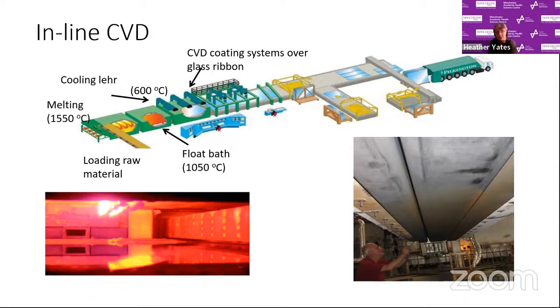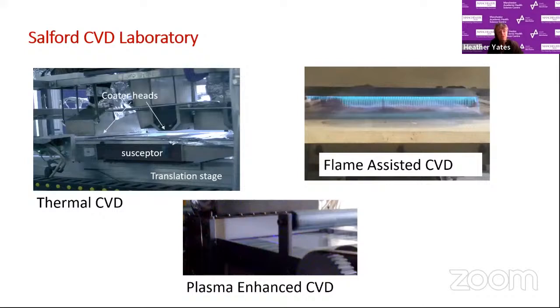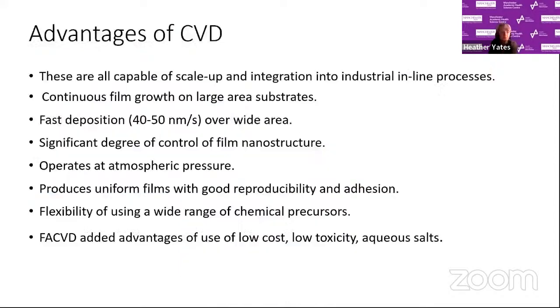Now, in my lab, I'm trying to mimic this process, probably not quite as impressive, but it works very well. So what I have is a choice of reactors where you have coating heads where the chemicals come down and they flow over the material I'm trying to coat, and then that moves along. But in my case, I have to move back to keep on increasing the thickness of the films. So I have thermal, where I'm just heating it, flame-assisted CVD, where you're using a propane air flame mixed in with the chemicals, or plasma-enhanced CVD, the example at the bottom, where you can see a purple glow of plasma as it's coating some thin plastic film.